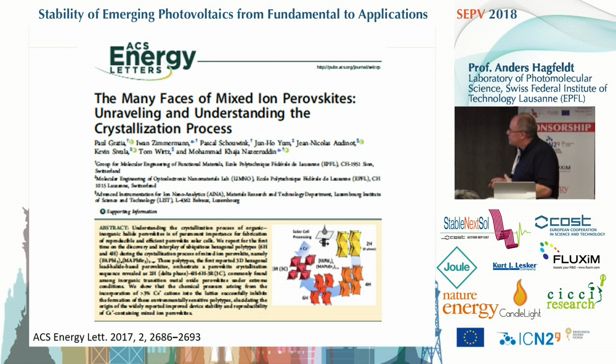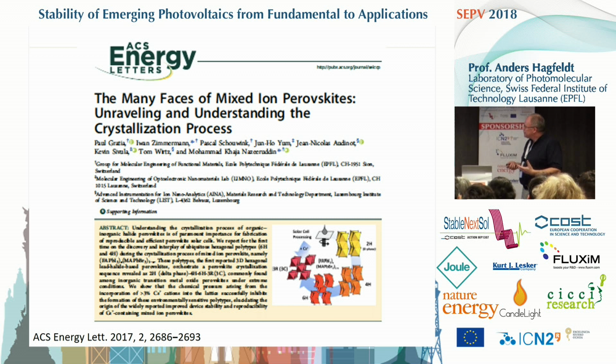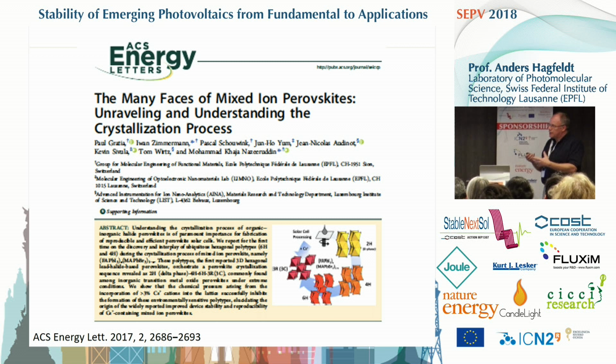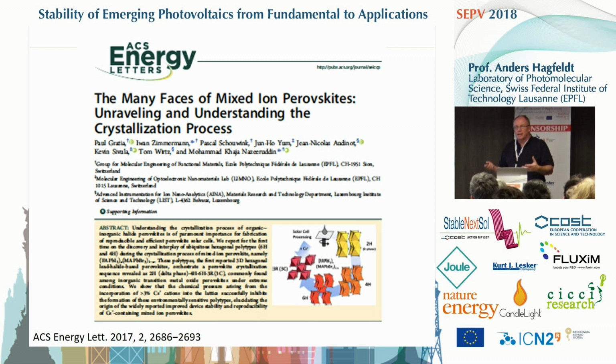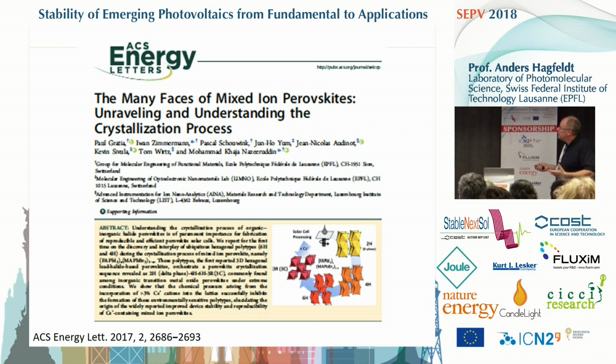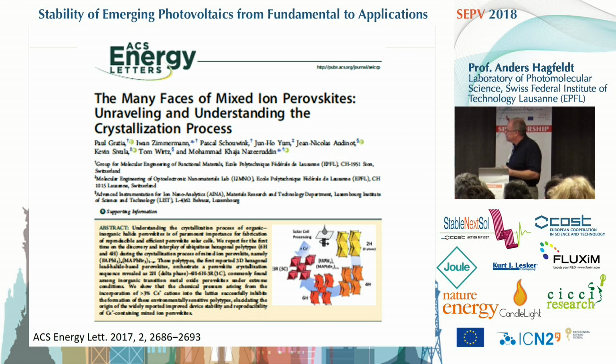They are environmentally sensitive. And what he showed in this paper is that when you add a few percent cesium, you inhibit the formation of these intermediate hexagonal polytype structures. And then it becomes less sensitive to the environment and so on. So if you're interested in the mechanism, this is a very interesting paper published in the autumn last year. Here you have the reference.